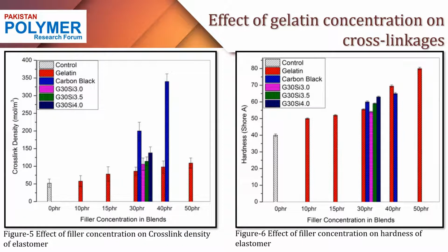As far as results are concerned, the first graph represents the effect of filler concentration on the cross-link density of the elastomers. Let me first describe the top left block showing the formulation. The control formulation is the one that possesses 0 phr of filler, with the red line showing formulations having gelatin filler in various phr starting from 10 phr to 50 phr. Then the blue line shows the carbon black filled elastomer. Then pink, green and dark blue colored blocks show the formulations having constant 30 phr of gelatin, with increasing silanized silica from 3 to 4 phr.